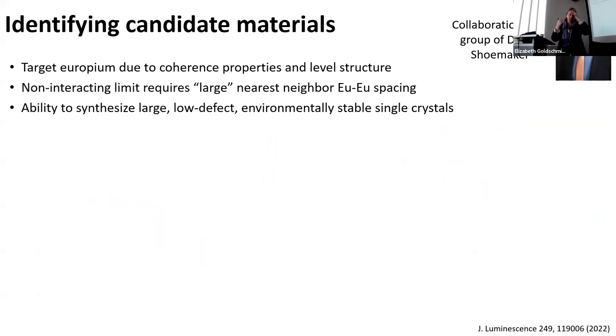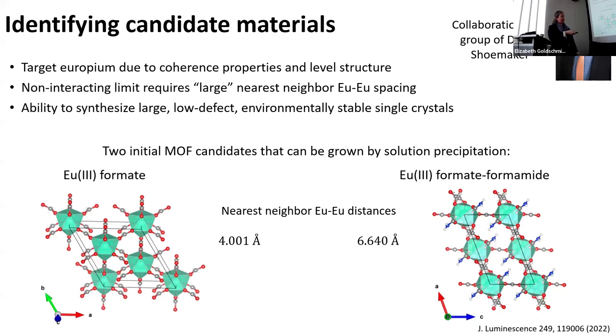Right, so we did a broad search of things that were in the literature and things that were almost in the literature. There was a terbium crystal in the literature, so we thought we could grow a europium crystal. We did DFT on some things, and we started identifying materials that had the properties that we wanted. Basically, the nearest neighbor europium spacing was kind of big on a solid state scale, but still sub-nanometer. And we thought we could grow things in solution and make decent crystals with relatively low defects. Our first results came out last year, and in that paper the first two things we tried were metal organic frameworks, MOFs, that have small and big nearest neighbor spacings.